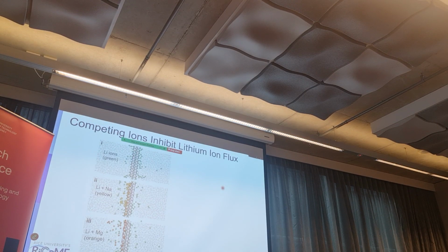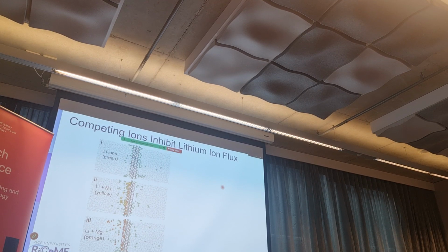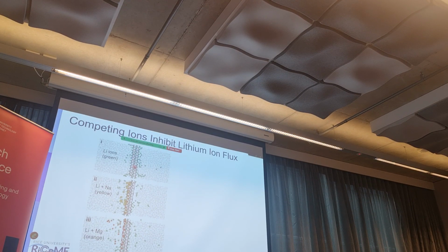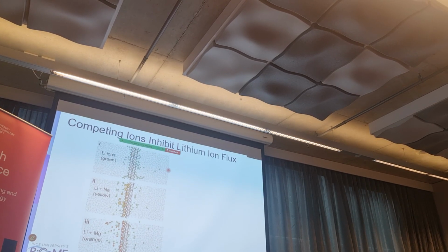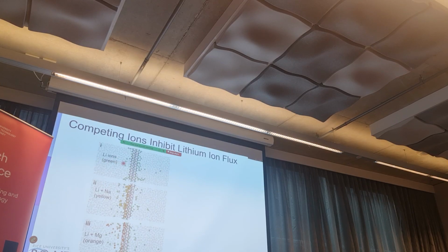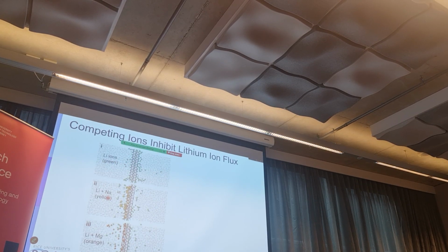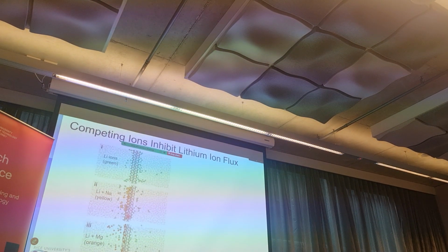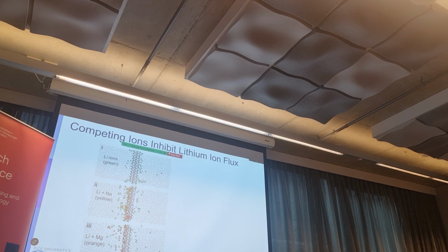We verified this with molecular simulation, taking a very thin layer of the top of the solid state electrolyte and simulating how lithium moves through it. We applied an electric field using non-equilibrium molecular dynamics simulations. With only lithium salt, shown in green, lithium goes through. With lithium and sodium, sodium shown in yellow only reaches the first layer, the first polyhedra, then cannot go through because of the bottleneck. The sodium gets stuck there while lithium continues through.